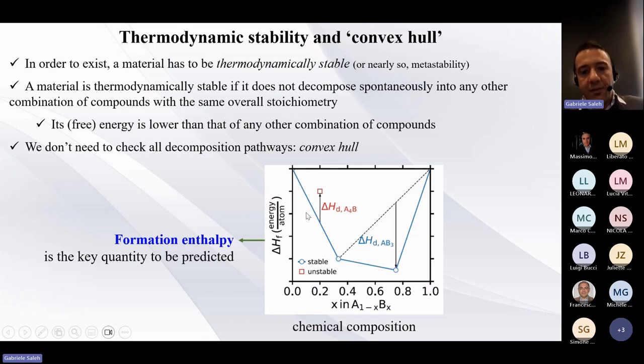The hull is the line which passes through the lowest lying points. And it can be demonstrated mathematically that a material is thermodynamically stable if it lies on the convex hull. Why am I telling you this? Because this simplifies the problem a lot. Given this convex hull construction, we are only interested in the formation energy to predict the stability, and this is a quantity which is much easier to calculate and also much easier to predict than the whole thermodynamic stability. So we just need to predict the formation energy to ascertain whether a material is stable or not.